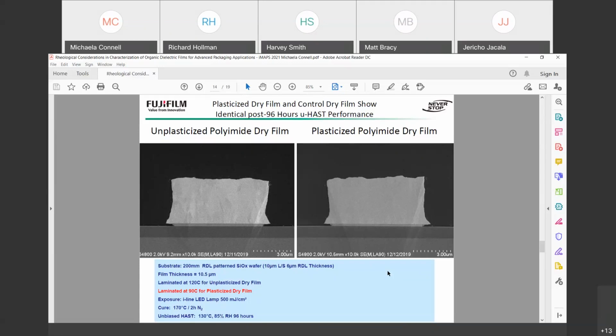The unplasticized dry film was laminated at 120 degrees Celsius, and the plasticized dry film was laminated at 90 degrees Celsius. Both were blanket exposed at 500 millijoules in i-line and cured at 170 degrees Celsius for 2 hours in N2. As you can see in the images, there was no effect of the plasticizer on the reliability of the film. Both had identical results.